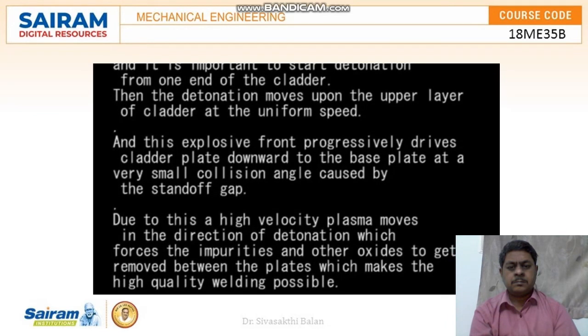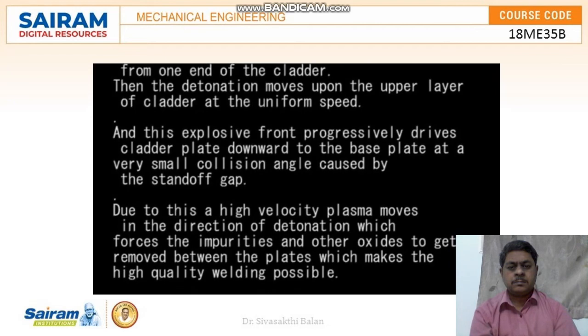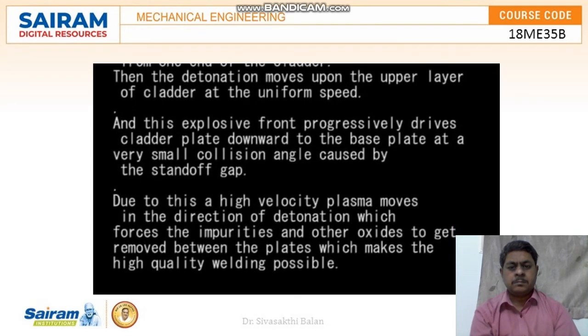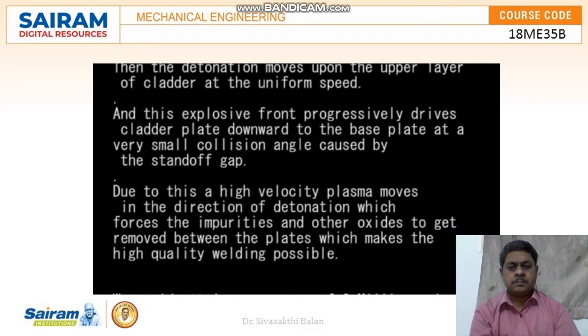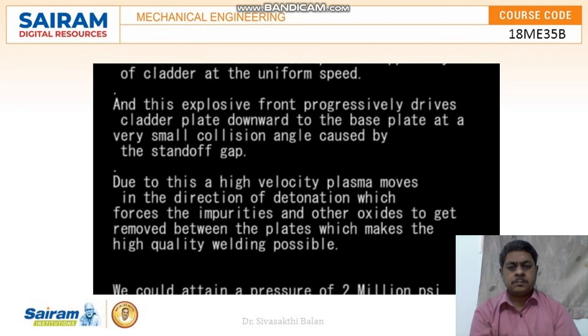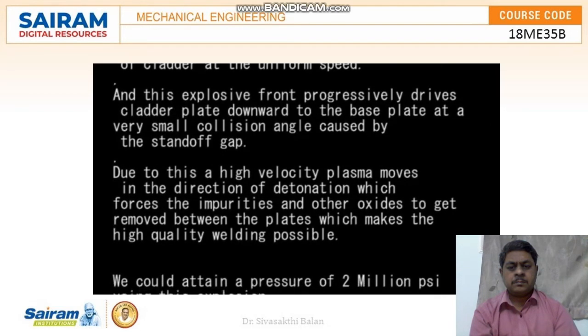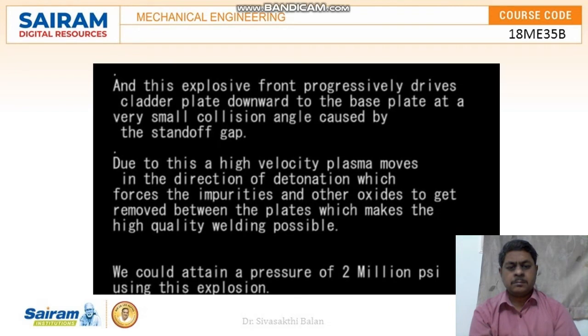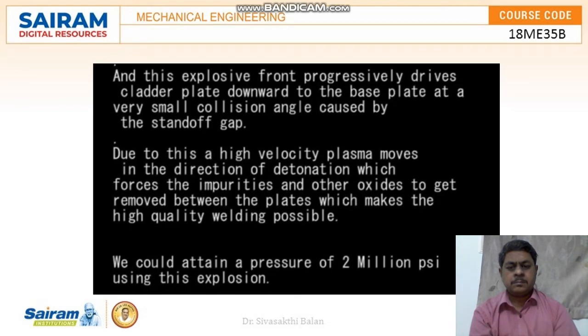Due to this, a high velocity plasma moves in the direction of detonation, which forces the impurities and oxides to be removed from between the plates, which makes high quality welding possible. Important fact: we can attain a pressure of 2 million pounds per square inch using this.